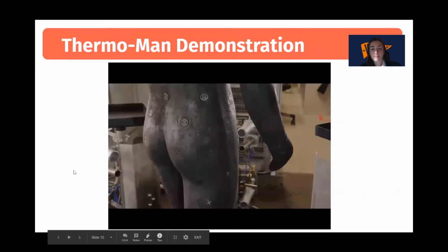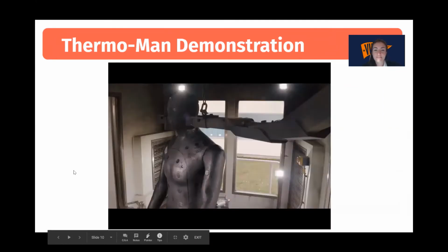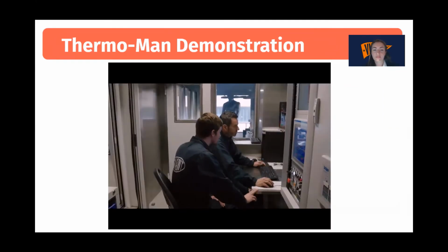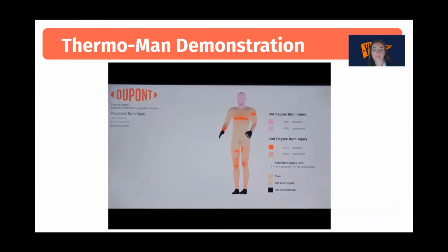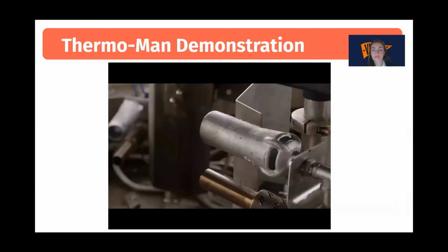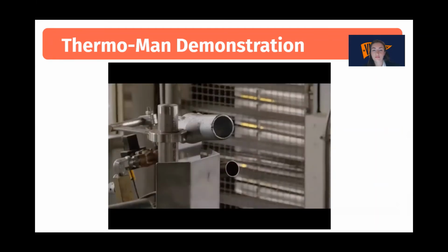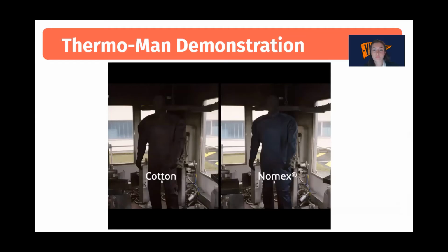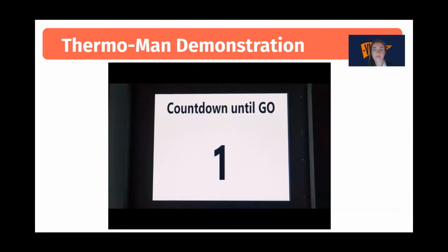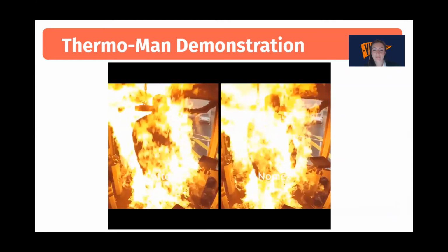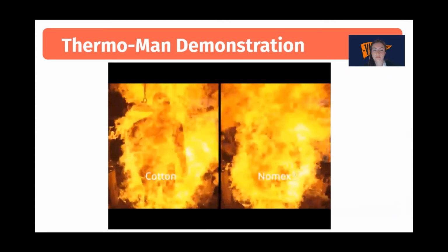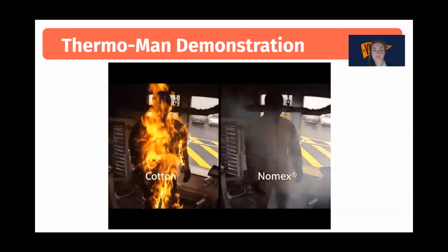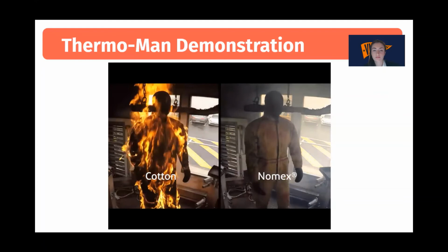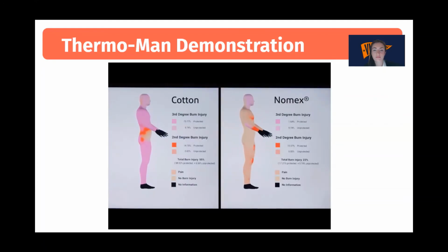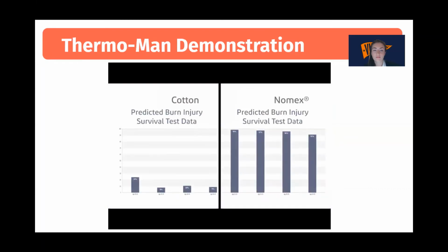Record the temperature rise on the surface of the mannequin. The computer calculates the predicted percentage of second and third degree burn injuries a person might suffer under similar conditions. Tests show that with exposure to the same flash fire, a worker dressed in cotton or polyester cotton could suffer combined second and third degree burns over up to 90% of his body. While for a worker protected by Nomex, the potential injury level could be contained to less than half, resulting in a lower degree of burn injury over a smaller body area, and thus substantially increasing his chances of survival and reducing recovery time.